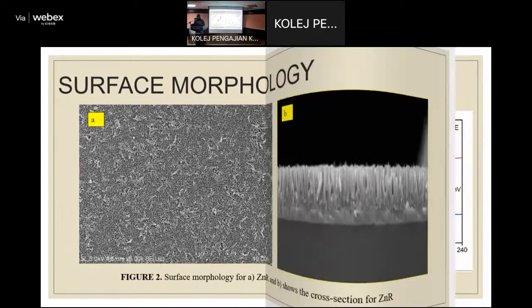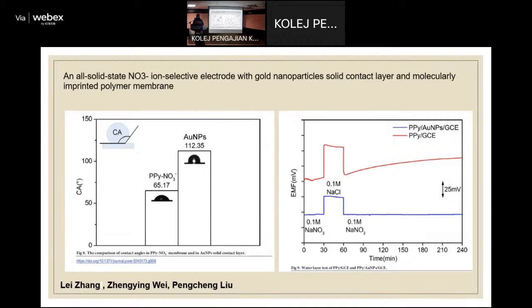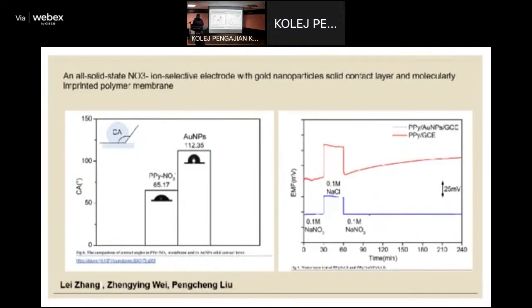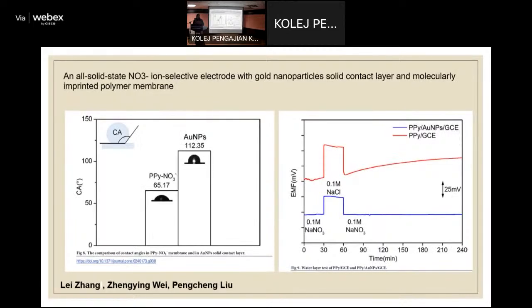Okay, for the nitrate sensor, the researchers have found it a struggle to produce a stable sample. So, for example, Lei Zhang et al. was trying to introduce gold nanoparticles on top of the sample to see the effect of the hydrophobic material on the stability of the sample. In order to see the stability, they tested with the water layer test, and they found that the gold particles help to improve the stability of the sample compared to the sample without the gold particles.